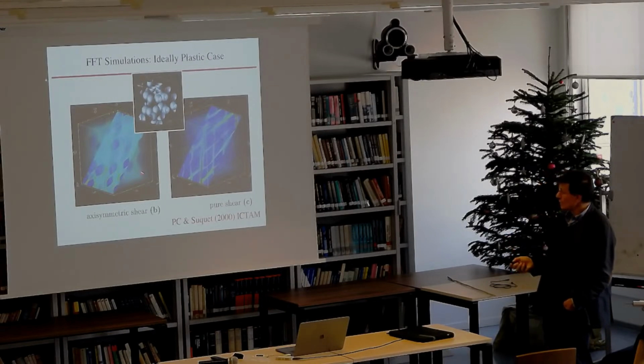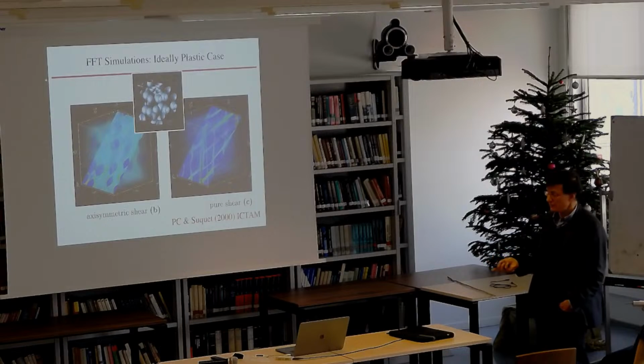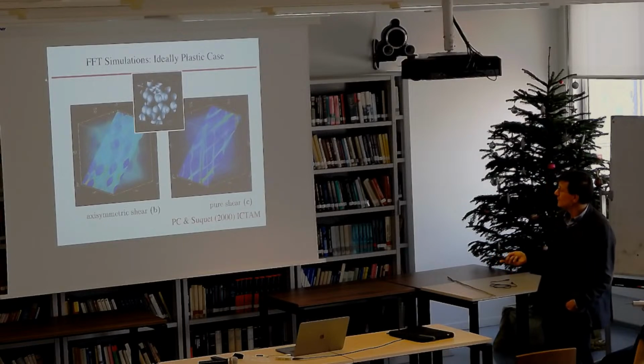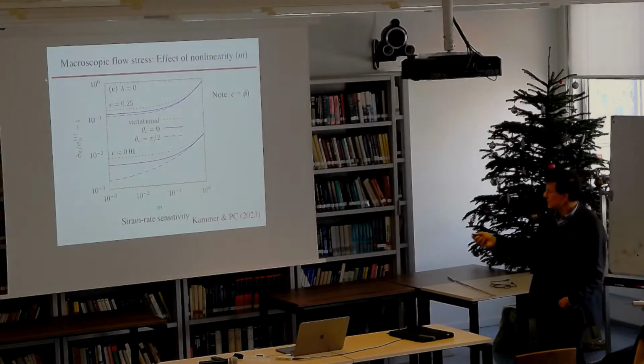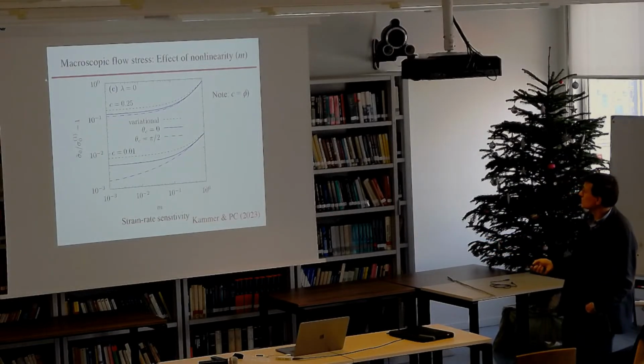So even though, if you do this for a linear material, you get the same macroscopic response. This suggests that the macroscopic response should really be different for nonlinear materials, in particular for ideally plastic ones. I'll show you what our results give.